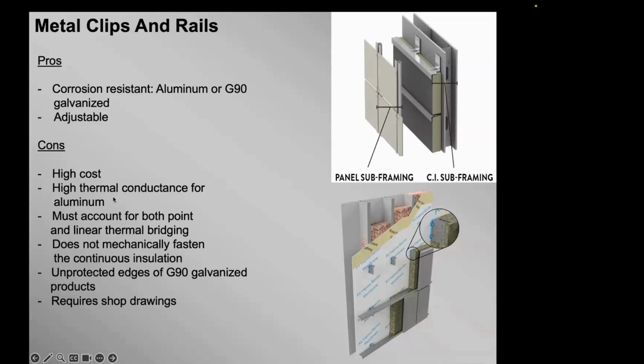The costs are high. The aluminum is very high thermal conductance. Like I said, you have to account for both point and linear thermal bridging. It doesn't mechanically fasten the continuous insulation. It'll retain it at the top, but I'd rather see it held on multiple points. And then if you're using the G90 galvanized, they galvanize a whole sheet and then they cut and bend and punch holes through it. So the edges where it's cut, I don't think are protected well. They have an argument for that, but I don't really agree with it. I'll show you that later.